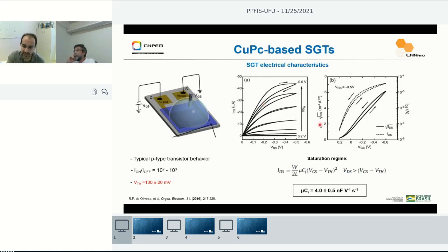If we plot the current or the square root of the current, you can also see the device switching from off to on. Again, there is some hysteresis. And from the slope of the curve, we can extract the threshold voltage, which is around 100 millivolts. The on-off ratio, the current ratio between on state and off state, can also be calculated from the curves.